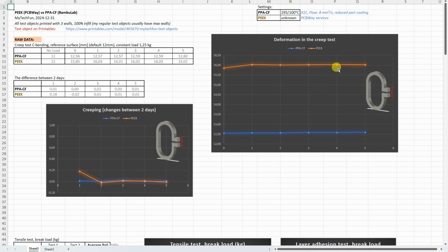we can see more deformation on the PEEK, but with the creeping we need the difference between 2 days, and that's what we can see on this graph, and these are extremely low values. The PEEK has some minimal creeping, but this was also very small on day 1, but after this basically it stopped with the creeping. I have some negative values here, probably some inaccuracy in the measuring, but in both cases these are quite good materials if you need resistance to creeping.